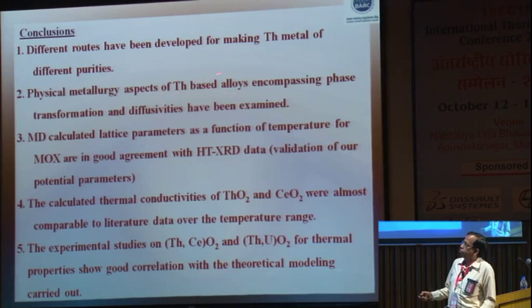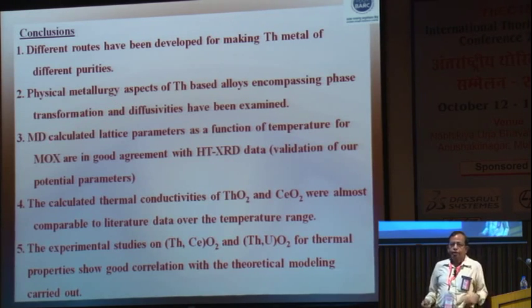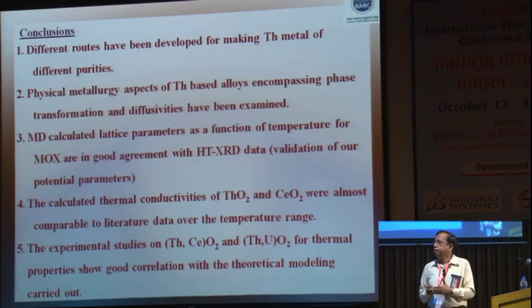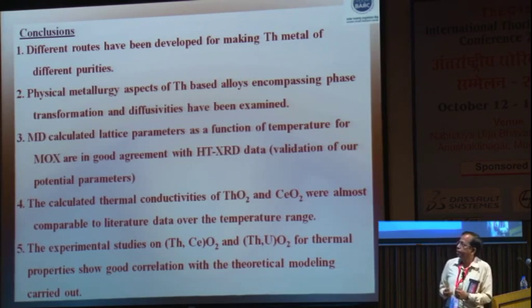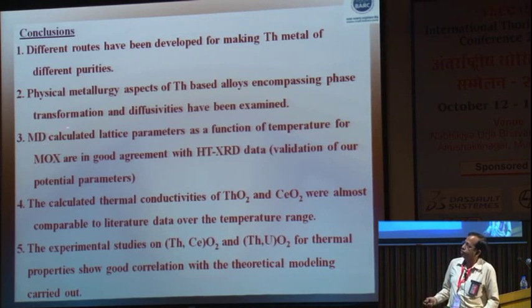Physical metallurgy aspects of thorium-based alloys encompassing phase transformation and diffusivities have been examined. I showed you an example of a diffusion couple made between thoria and zirconia for studying diffusivity, and some results on phase transformation. Actually, getting pure thorium is not so easy, because all the thorium that we end up getting does have some amount of oxygen, and only recently we have managed to get thorium which is reasonably pure in terms of oxygen content. Thoria is always very good with us, and that has never been a problem.